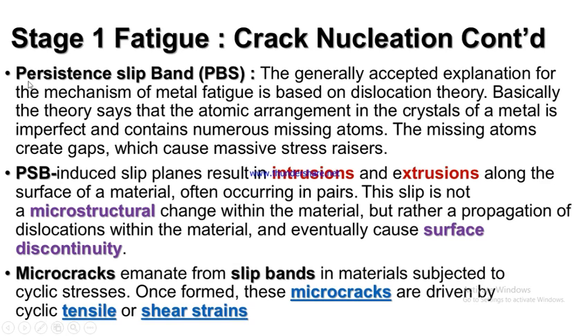Now let's look at crack nucleation continued. Like I told you before, sometimes we may not have a crack initiation site, we may not have an inclusion or imperfection in the material. Basically, sometimes we have what we call persistent slip bands, which can also lead to crack initiation in the material.